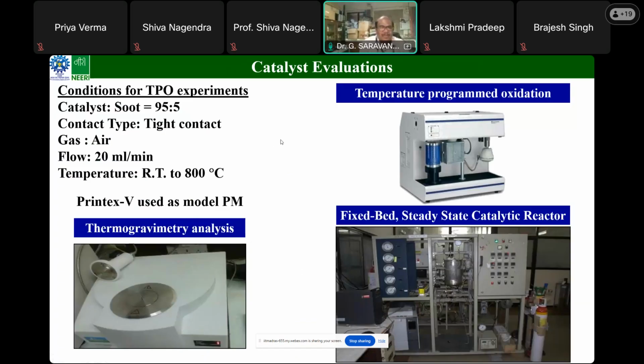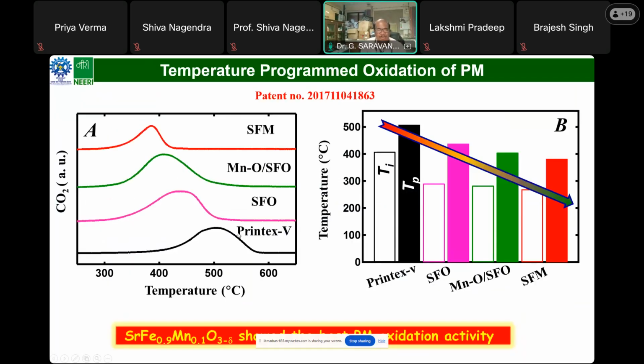Anyway, we have done catalytic evaluations, both in a conventional fixed bed reactor as well as temperature programmed oxidation experiments. We mixed the catalyst, strontium ferrite, or manganese substituted strontium ferrite, with soot in this ratio, and selected tight contact conditions. This is Printex V, a model particulate matter, and this is strontium ferrite. This is manganese oxide, a reference catalyst, and this one is manganese substituted strontium ferrite.